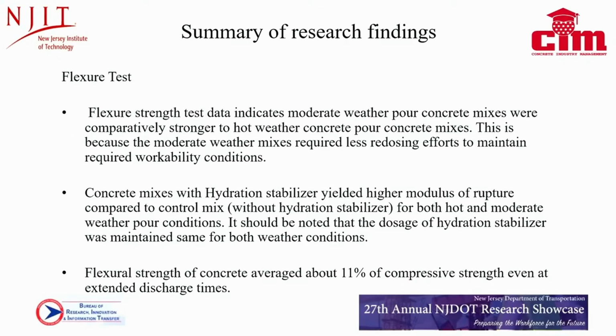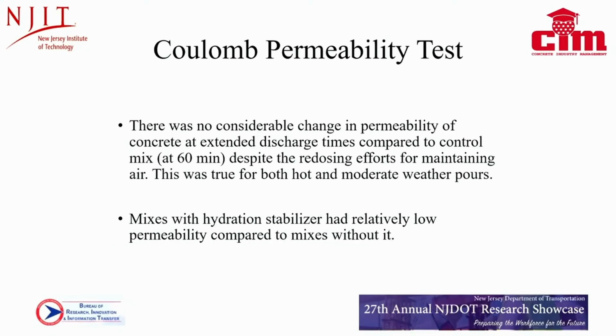The ones with hydration stabilizer basically gave us better results. The flexural strength was good, about 11% of compressive strength. Okay, there was no considerable change in permeability. The permeability tests were fairly consistent across all timestamps, 60, 90, 120, 150. So we basically were doing tests every 30 minutes.